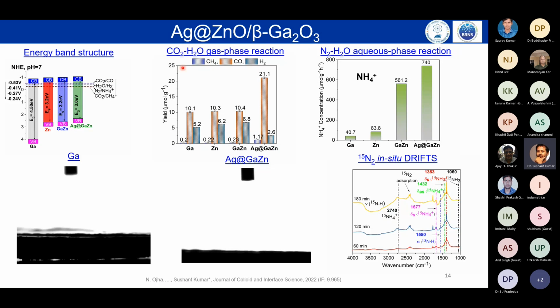Now here you see the yield percentage for methane, CO, and H2, and it was silver which was giving a lot. Then this was the ammonium ion, which we measured, and we also characterized it by in situ DRIFTS with 15N nitrogen, and you can see that those reactions are possible, and that 15NH3 and 15NH4+ are present. We have seen the bending vibration and the stretching vibration. This is for the stretching vibration, this is for the bending vibration. So those species were present in the spent catalyst that we have.